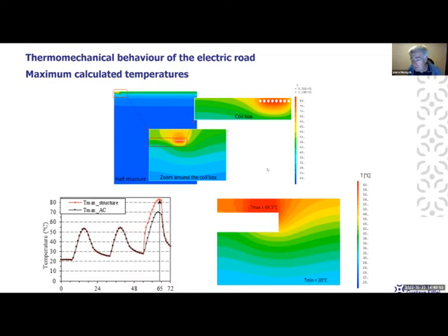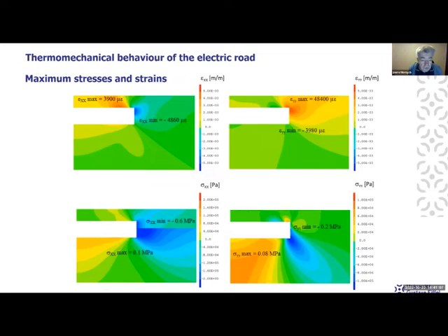In France, we consider that typically, the maximum temperature to avoid excessive rutting is about 60 degrees. So with these charging systems, you can exceed these temperatures in hot summer conditions. And here you can see the stresses and strains generated. So we have to continue this work, but it is clear that you generate stresses and strains, especially at the corners of the coil block when the temperature increases.